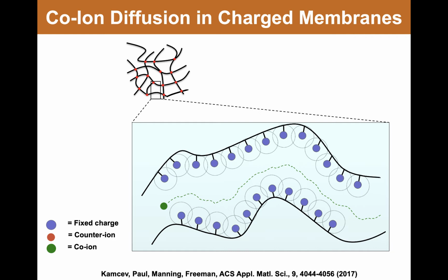So there's a driving force that moves it from left to right. And in taking these diffusion steps through water, the ion is excluded from going through the polymer chain, and it is also trying to minimize electrostatic interaction with the sulfonate groups that would have opposite charge. But basically, it is just diffusing through this network, avoiding the charged groups, and having to diffuse around the polymer chains. And so there's two variables or two phenomena that are at play here.